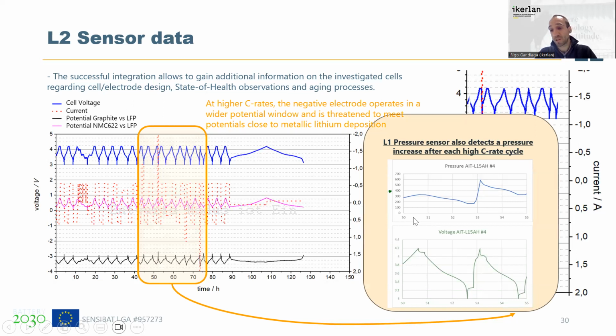This is also something we measure, but in a completely different way, with the L1 sensor. In this case, we measure an increase of pressure every time that we perform this 3C charge, and this increase of pressure is not reversible.